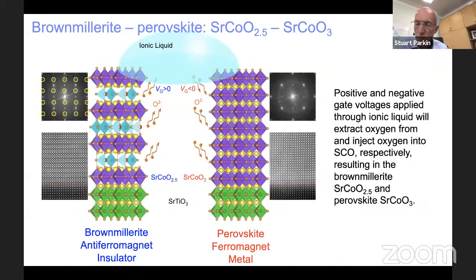And so since I came here, we could use these ionic liquids to gate an oxide device within the transmission electron microscope. And the system we chose is this one, strontium cobalt oxide (SrCoO3), which is a perovskite. And you can see on the right-hand side, it's a beautiful cubic structure. This is in the transmission electron micrograph. These films of strontium cobalt oxide we've grown by pulsed laser deposition on strontium titanate, shown here.